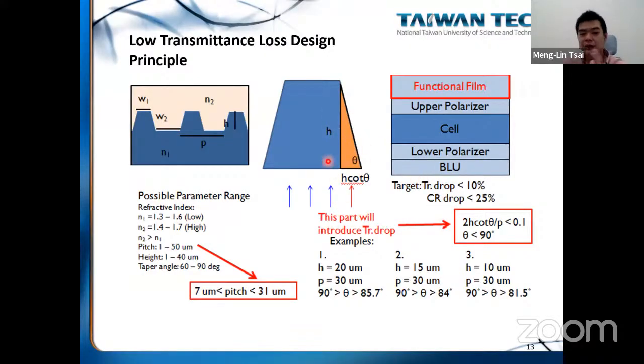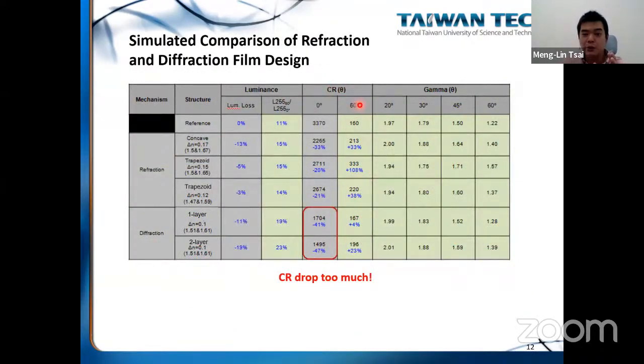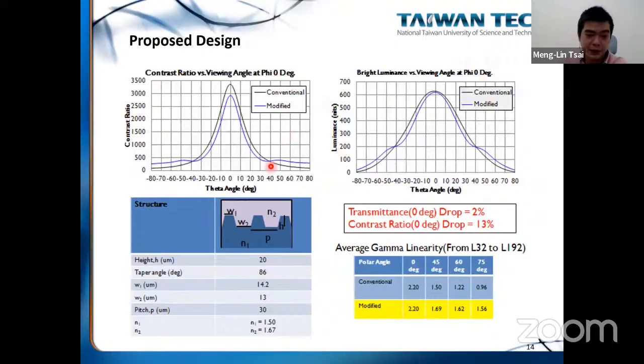The transmittance drop can be determined by this angle here. We assume that we come up with a trapezoid structure. The transmittance drop is determined by the angle and the height ratio of this part here. So we can do some simulation to control the transmittance drop. But later on we still need to compare the goal of the contrast ratio we want at the large angle and the goal of the contrast ratio for the normal direction. So we can come up with this kind of figure to evaluate.